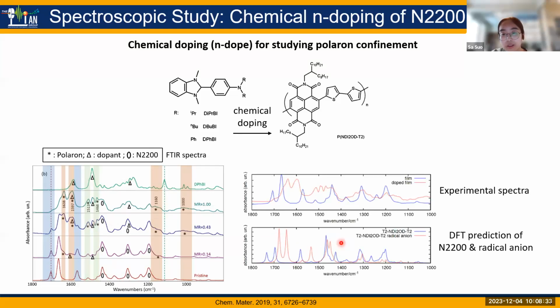They further did DFT calculation to predict what could be the polaron structure. So the top panel shows the N2200 peak and also the doped IR spectrum. And their DFT calculation predicts pretty well the N2200 itself, and also they predict if the polaron is localized as the radical anion, this red spectrum will be the IR spectrum, and it also aligns pretty well with their experimental spectra.